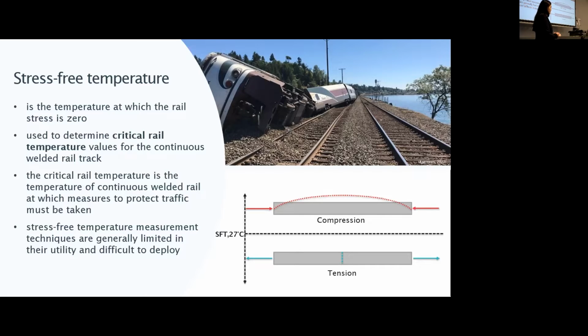Also, the stress-free temperature is used to determine the critical rail temperature, which is the temperature at which measures to protect the traffic must be taken, and usually it is speed restrictions. However, it is not easy to measure the actual stress-free temperature in the rail, as the measurement techniques are generally difficult to deploy. Thus, it is important to understand the factors affecting the stress-free temperature so it can be easily estimated and the correct critical rail temperature can be assigned to prevent any accidents.